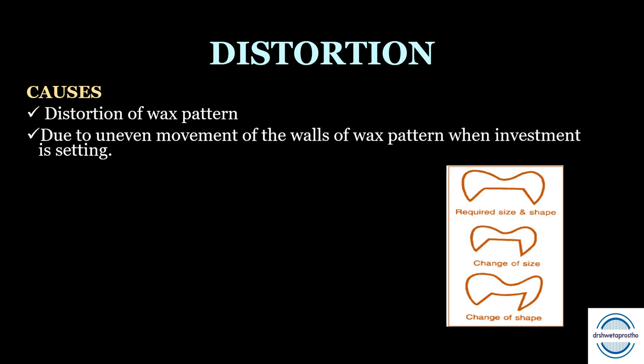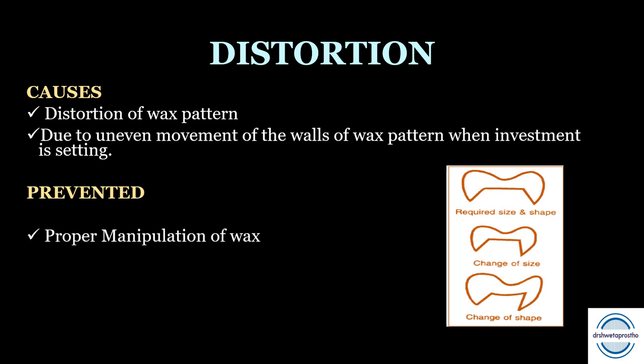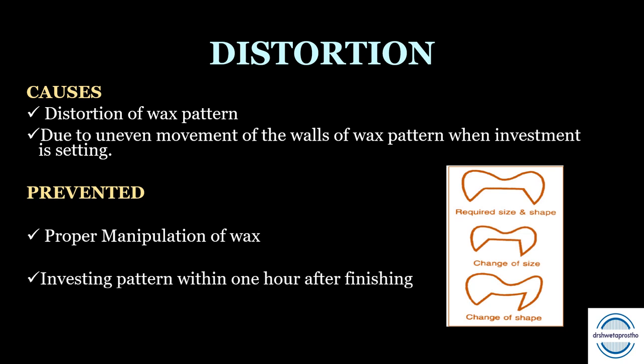Prevention of distortion depends on removing the cause. First, proper manipulation of the wax during pattern fabrication and carving. Second, the investing of the pattern should be done within one hour after finishing — as soon as possible. If storage is necessary, store the wax pattern in the refrigerator so that minimal stresses are produced.